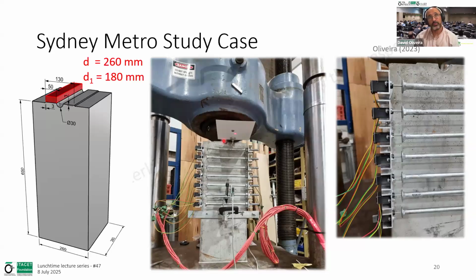So we could make use of what the FIB Model Code mentions as verification assisted by testing. So we produced samples of our segment joint here. Of course, not the full 1 meter, it was limited to the same thickness, but we introduced very high concentrated loads. You can see here the loads were applied only in this red zone, only 50 mm. So the joint is a very small joint, only 130. And we applied the loads with very high eccentricity to understand how this joint sample would perform in terms of